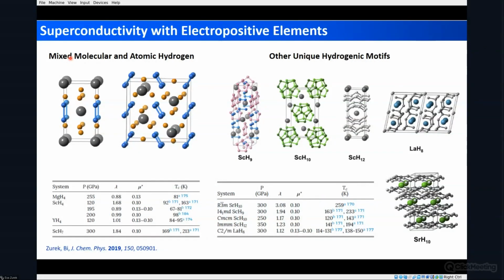Again, if you have systems with mixed molecular and atomic hydrogen, they are usually similar to the ScH9 case that I talked about earlier, and TCs at various pressures, these are predicted TCs, can go typically up to about 100 Kelvin, though there are some exceptions, such as in ScH7. And the reason for this exception is because the valence of scandium is actually going to be 3+, and there is some electron charge donated to these H2 units which is going to lead to the metallicity.